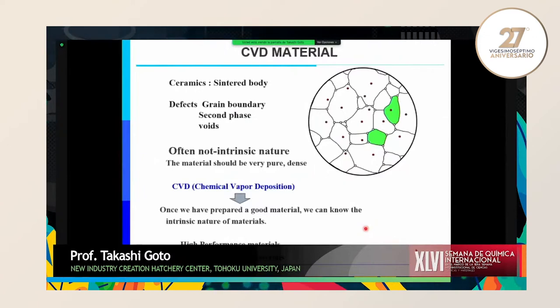So alumina and silicon nitride, often called ceramics, are usually prepared by sintering, and the sintered material usually contains grain boundaries, second phases, pores, and voids. The property of ceramics may not be the intrinsic nature, but it may be the nature of impurities and defects. So in order to know the intrinsic nature, or in order to realize good nature of materials, we have to make very pure, very dense materials. So CVD is a very good way to make good materials. Once we have prepared good material, we can know the intrinsic nature of materials, and we can make a high performance material, or we can find a new application of materials.